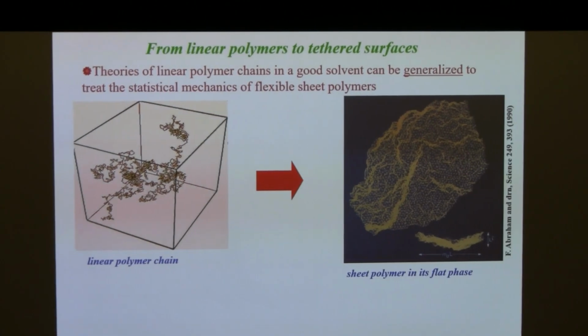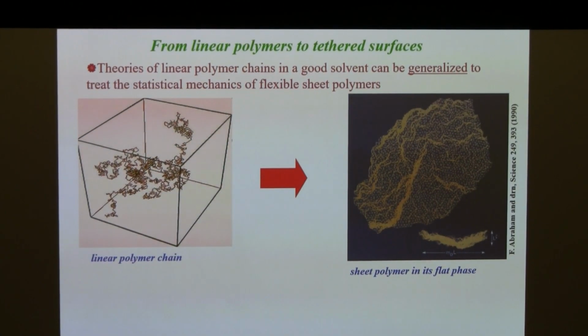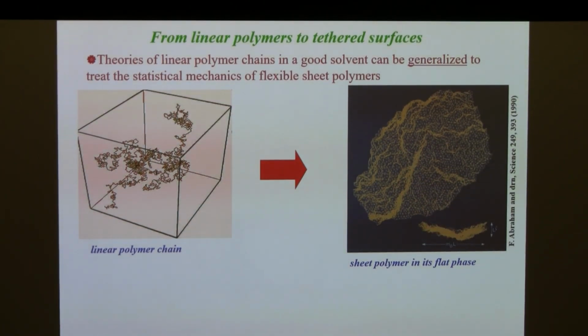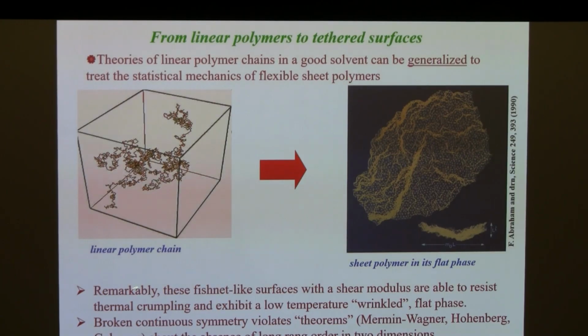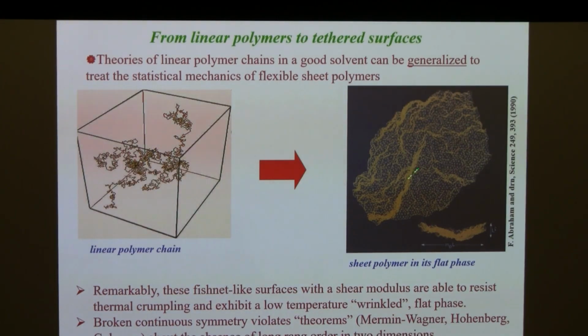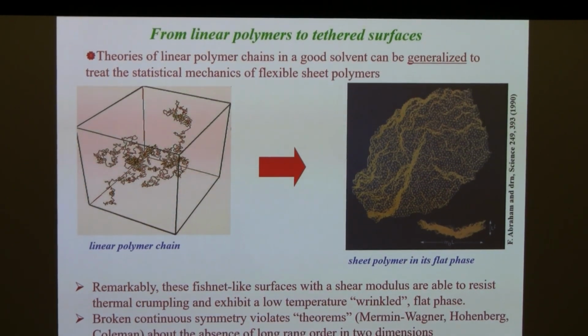And the normals, there's long-range order in the normals, which you might have thought would be like Heisenberg spins, 3-component spins. There is long-range order in violation of some theoretical expectations. There's a broken continuous symmetry that violates various theorems for good reasons. It's not that the theorems are wrong. It's that when you have a shear modulus, as you'll see, new kinds of physics arise in these kinds of rippled surfaces. And there's a nice, fairly recent review by Katsnelson and Geim about this seeming contradiction of a venerable theorem in statistical mechanics.